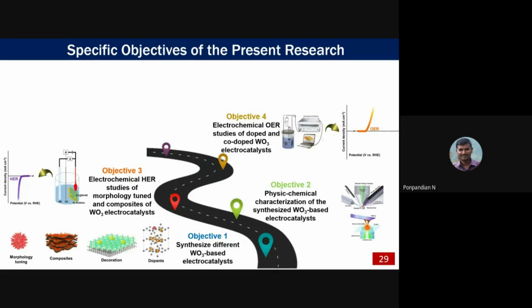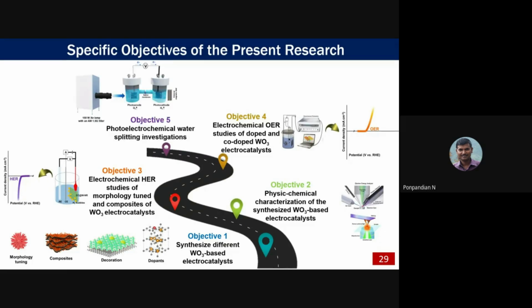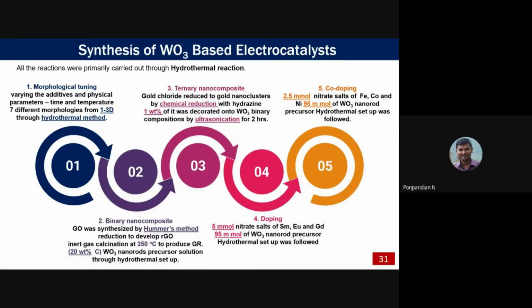For that we are making some other material based on co-doped tungsten oxide, with iron, cobalt, and nickel. Next one, objective 4 is actually the OER. Objective 5 is photoelectrochemical water splitting, and finally a full cell reaction. Here we made a device to make a full cell reaction. There one cell will produce hydrogen and another cell will produce oxygen. In that way, when you are splitting the water, you are able to extract both oxygen and hydrogen for commercial purposes.